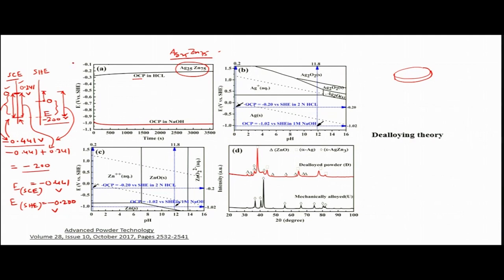We measured the OCP of the pellet versus the SCE and converted everything to the SHE scale, because the Pourbaix diagram is referenced to SHE. This gives us the potential of the alloy in that particular solution. We then took Pourbaix diagrams of silver and zinc from standard references and plotted the measured potential alongside the solution pH (2 normal HCl), which was around −0.2 to −0.4 V vs. SHE.